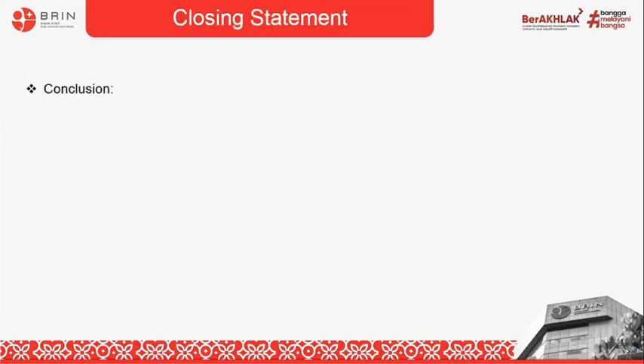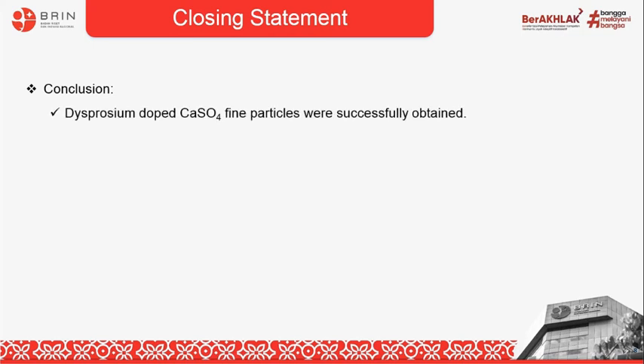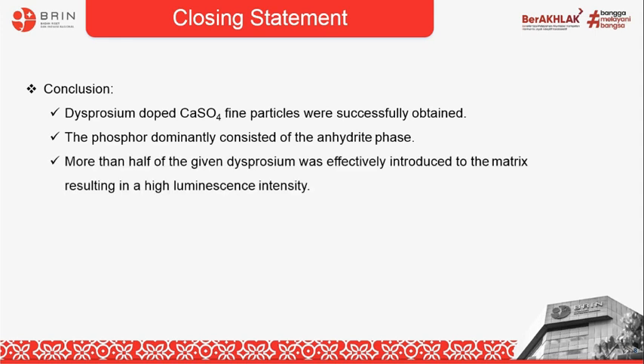For the closing statements, we could mention that dysprosium-doped calcium sulfate fine particles were successfully obtained using a wet chemical synthesis route at pH 5, followed by heat treatment from 90 until 650 Celsius degree. And the phosphor dominantly consisted of the anhydrite phase with mass concentration up to 97% based on the semi-quantitative analysis. More than half of the given dysprosium was effectively introduced to the matrix, resulting in a high luminescence intensity which indicated a sensitive phosphor toward low dose beta exposure, despite the non-uniform particle shape and size.